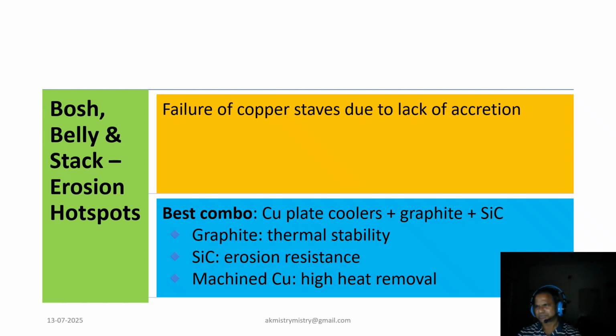Coming to the Bosh, belly, and stack, in particular the lower stack region, here erosion hotspots are very prone. The upper zones contend with erosion because here a lot of huge mechanical motions occur, and wear due to gas burden interaction also and copper stave degradation. So a strategic mix is essential. Machined copper for heat withdrawal, graphite for thermal buffering, and silicon carbide for erosion resistance. This triad strengthens wall resilience and supports accretion formation, guarding against premature failure.